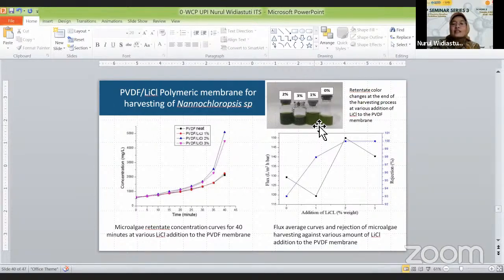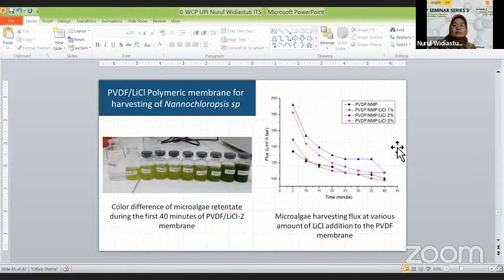And this is the result of the harvesting of Nannochloropsis. Here we can see the retentate color change at the end of the harvesting process with the addition of lithium chloride to the PVDF membranes. And this is the selectivity and the flux. The selectivity we call the percent rejection, and also the flux of the microalgae. We can see the rejection percentage reaches up to 100% here. And this is the color difference of the microalgae retentate during the first 40 minutes of the PVDF lithium chloride membranes. We see the different color degradation here.